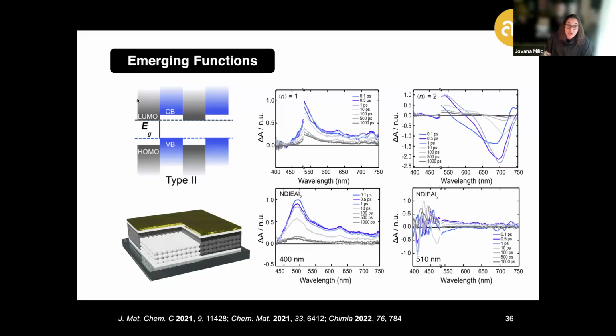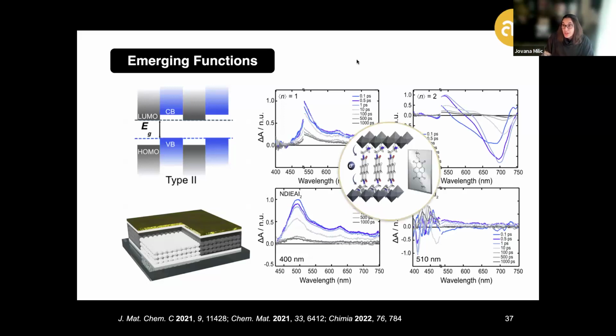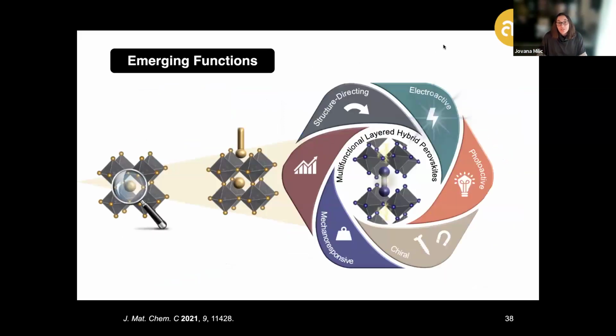This suggests accordance with inverted quantum well architectures where there is more direct exchange between the organic and inorganic component, setting the basis for relying on these systems in alternative functional roles that not only involve acting as the active absorber inside conventional solar cell architectures, where these systems are typically sandwiched between selective charge extraction layers, but also taking perhaps the role of some of these charge extraction layers in addition to their stabilizing role.